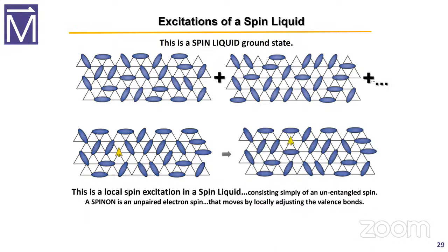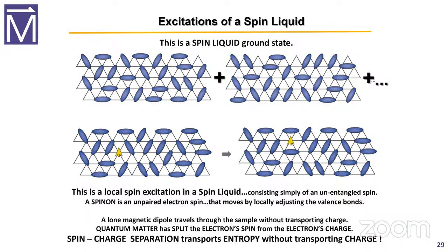All we're going to do to go from here to here is have this singlet no longer pair those two electrons, have it pair these. The singlet had just moved from this site up to this site. So you're moving the spin of the electron without moving the charge. So a lone magnetic dipole can travel through the sample without transporting charge.